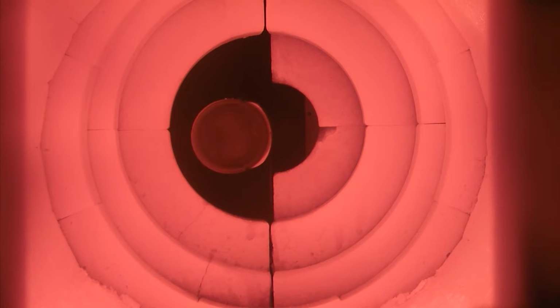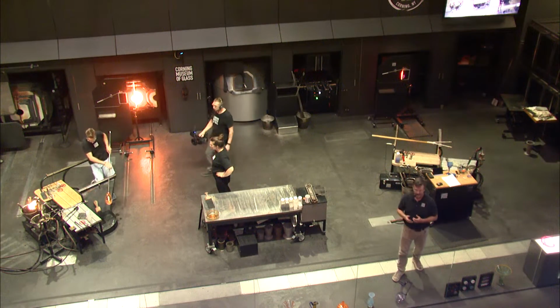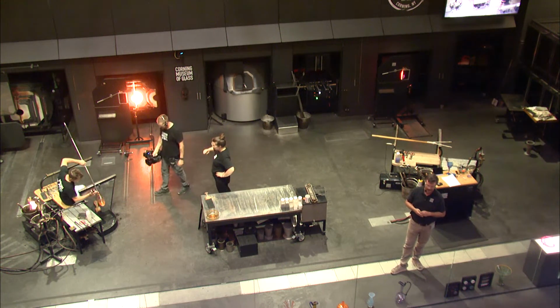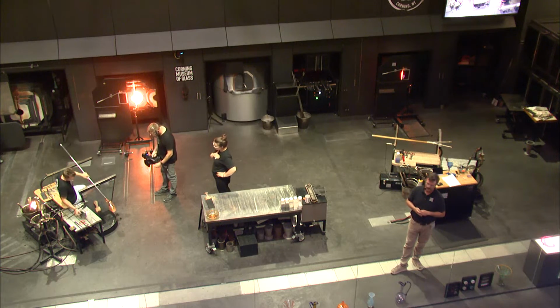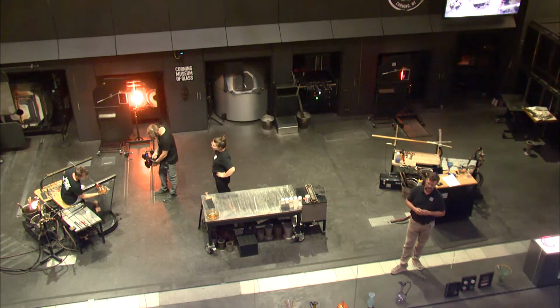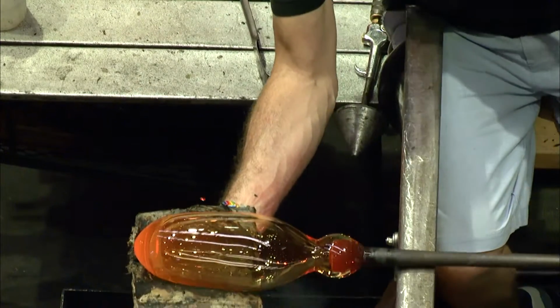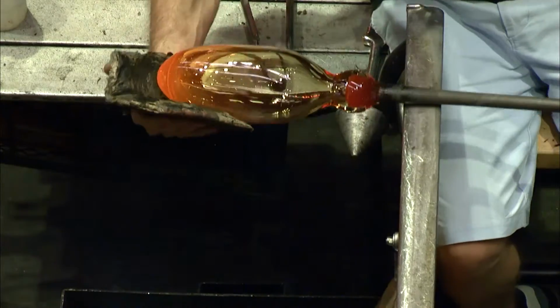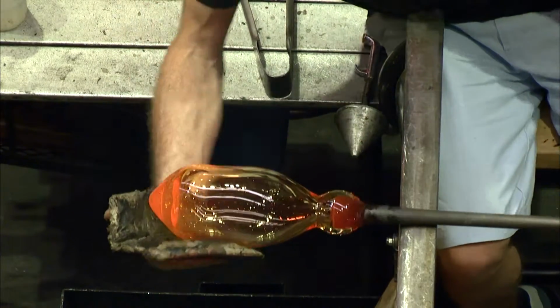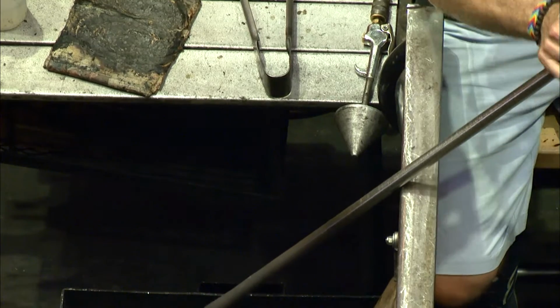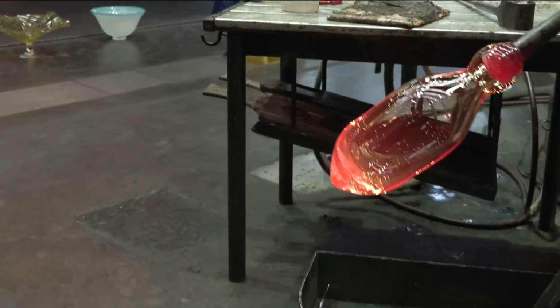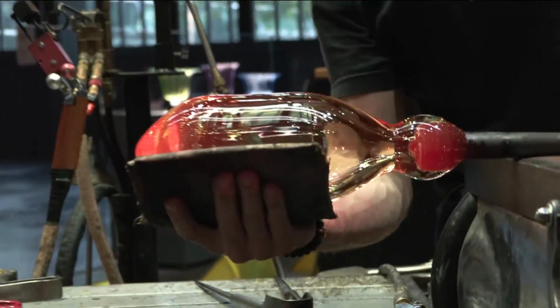However, it is very brittle, and the more you fire it up and cool it off, the more brittle it becomes. It starts to fall apart. We fired that furnace over a period of a week, and it was kind of falling apart. We did that for the filming for the Dig Deeper show and the footage that you see in that exhibition of people working at the wood fire furnace. That's us working at our first iteration.